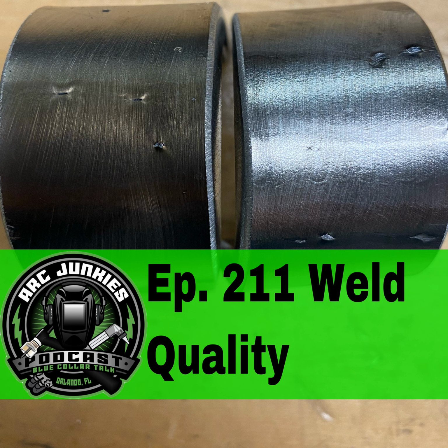In addition to that, incorrect welding conditions or techniques, such as arc length. Arc length is such a huge factor in pretty much all of the weld discontinuities we're going to talk about. So if my arc length is too long, that means I'm not getting adequate gas shielding for flux core, gas shielded, or gas metal arc welding, but also with stick welding, because as we're melting an electrode, that's going to create CO2. That's where our shielding gas is coming from. And we want to make sure that we maintain a proper arc length, so as that flux burns off and creates that CO2, it's within our weld pool area. So we want to make sure we maintain a correct arc length. So that's one thing we can do to eliminate porosity.